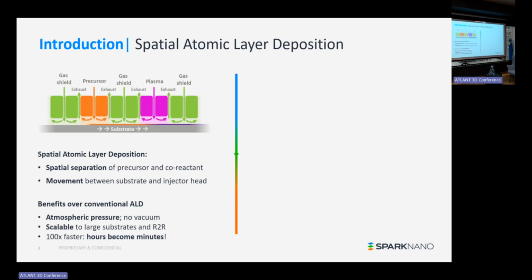So what we do is spatial atomic layer deposition, and this morning it was already explained a bit by Eric Gessels. Basically, what we do is ALD, but we use a spatial separation of the precursors and co-reactants instead of temporal separation. We do that in a so-called ALD head, which is technically similar to what ATLANT is doing, but bigger. It's the same width as the substrate. It's based on spatial separation of precursors and co-reactants, hence the name spatial ALD. And there has to be a movement between the substrate and the ALD head.